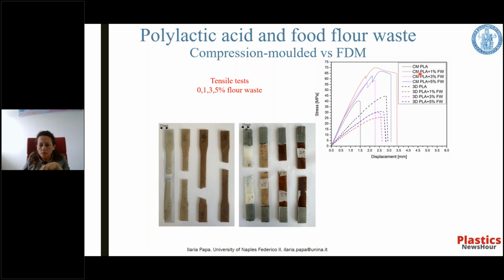This variation could be due to the raster angle of the deposition, equal to plus or minus 45 degrees. So during the printing process, the floor waste particles don't align along the printing orientation, as also demonstrated in other literature. And on the other hand, the assembly of filaments in FDM cannot prevent holes between filaments, the superposing of filaments, reducing the mechanical properties. Under similar process conditions, this effect is expected to be greatly reduced for compression molding, as the samples are subjected to high compaction pressures during the production.